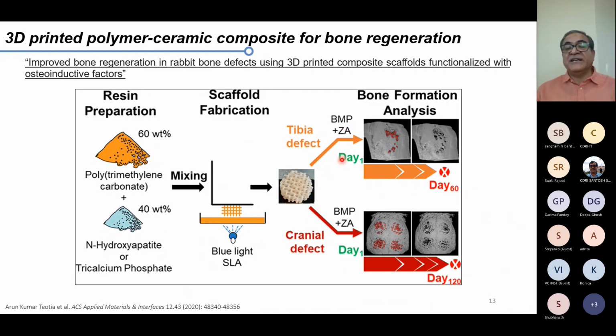We kept this tibia defect for 60 days, and we kept the cranial defect for 120 days. That's the duration typically you may need. 4 months, 2 months, I can say is the shortest period. That can only be possible if you are using bioactive molecules. Otherwise, it takes longer than that. But cranial may take longer because it's a large portion of the bone to come back. So you may take a longer time, that 120 days.